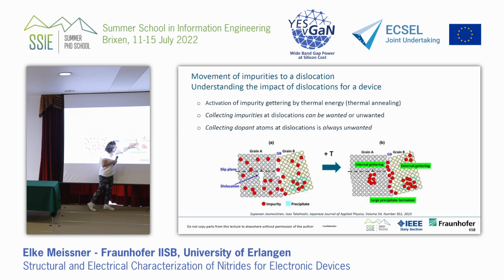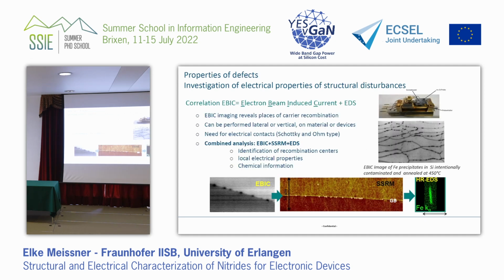But then the foreign atoms go to this place where you have stored high energy, where there are the dislocations. And this is what you can measure. We heard already this morning an EBIC measurement example, so electron beam induced current. We combine this with an EDS measurement. So it's a measurement where you can have information about the chemical content at the same time, where you get information about recombination places.